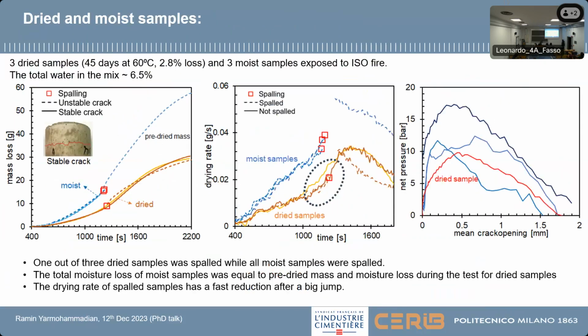And then to understand more what is the real role of moisture, we have these tests in which we semi-dried 3 samples, and we tested 3 moist samples and 3 semi-dried samples. You see 3 out of 3 moist samples spalled. On the other hand, 1 out of 3 semi-dried samples spalled. This shows that moisture is the leading and crucial parameter. And then you can see that the drying rate after this spalling has a fast reduction, while in the other one, when it is not dry, you do not see this fast reduction.